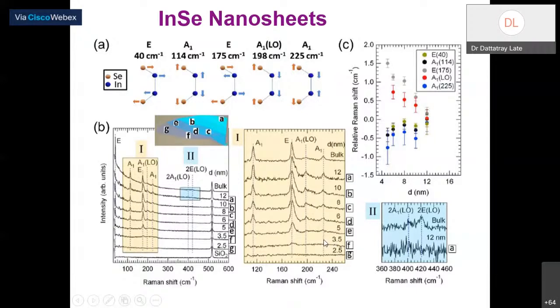Of course, the one layer of indium selenide thickness is around 1 nanometer, because we have indium in between and selenium on both the sides. This makes one layer of indium selenide. You see, at 3.5 nanometer, all the peaks, all the spectra disappear. This was a very surprising thing.